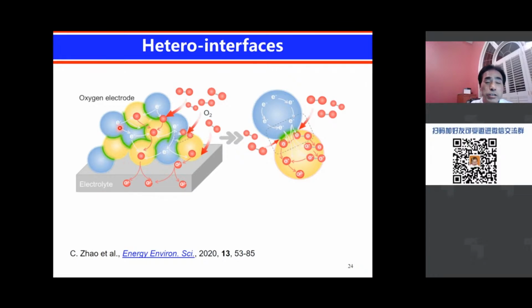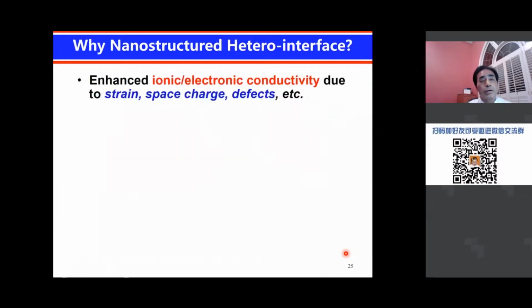Now, another simpler way is just using nanoparticles of different materials. You have a mixture when they mix together, and even if it is random, if the particle size is very small, you actually can create a large number of active sites for a porous electrode. Now, why do we need nano hetero-interfaces? From a scientific point of view, this type of nanostructure is going to significantly enhance catalytic property because it could create a strain across the interface or induce a space charge region. You could have accumulation or depletion of certain charged species or form certain defects at those junctures.